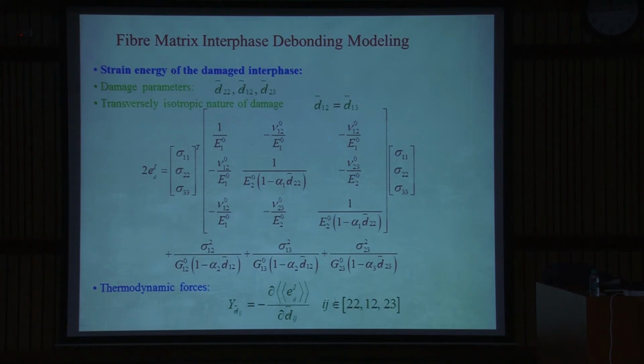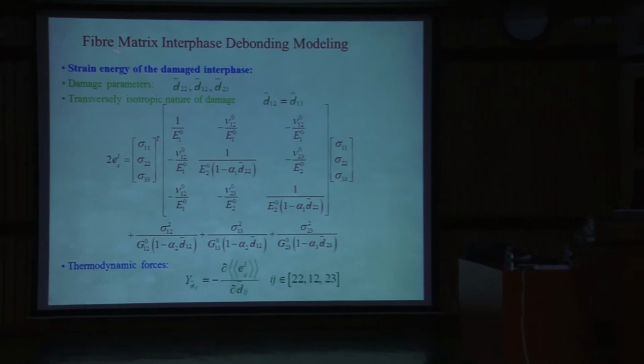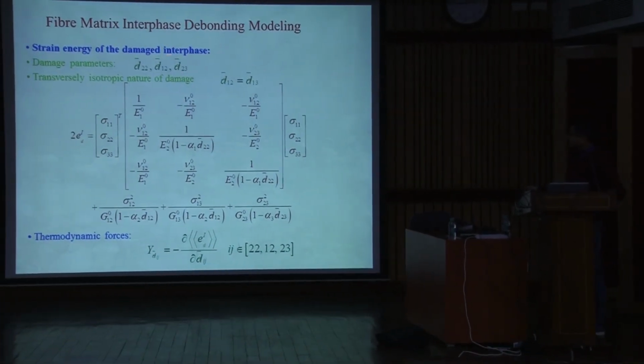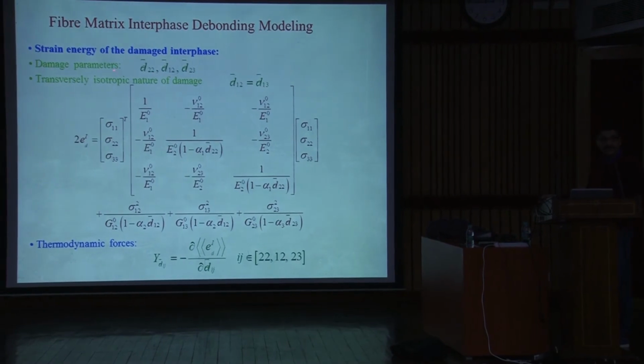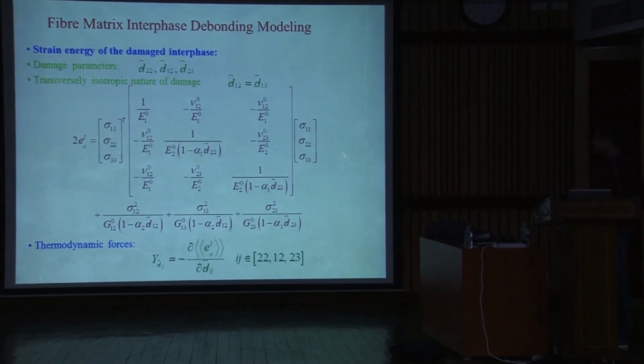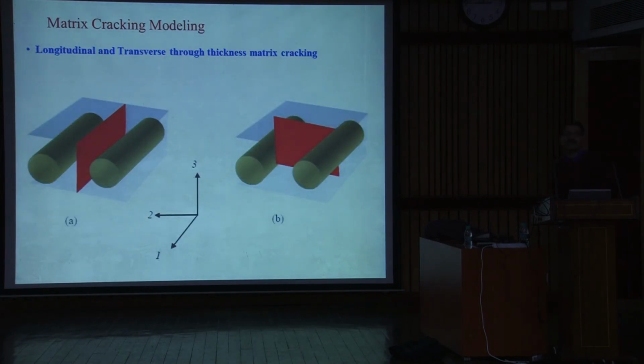So if I am considering only the fiber matrix debonding, and if I consider all these effects, then the strain energy that I get is this, and for these damage parameters I can have the associated thermodynamic forces which are defined like this. So this is the next mechanism, which is, as I said, the transverse cracking. There are two possibilities. These cylinders are nothing but these fibers. So the crack can be longitudinal or the crack can be perpendicular to these fibers.